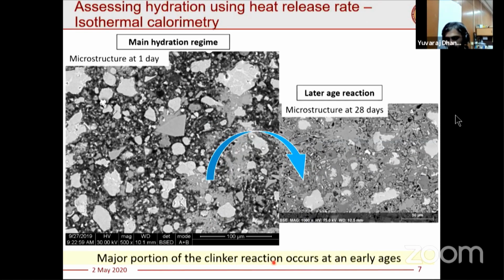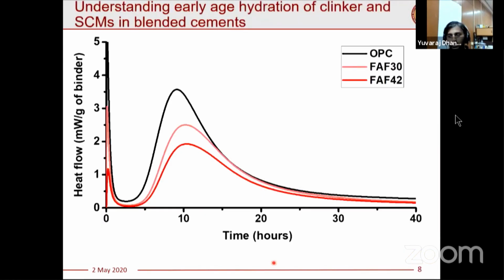So let's look at what happens when we put an SCM or a mineral admixture into it. These are some hydration curves with fly ash at 30% and fly ash at about 42%, and high volume fly ash. You can see because the clinker is less, the clinker reaction total heat flow is reduced, and there is also a delay in the increase in the heat evolution curve. So let's look at whether the addition of fly ash as such is having an impact on the reaction of the clinker phases. How do we do it?